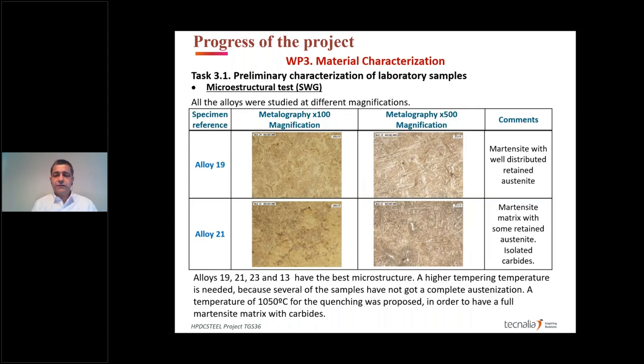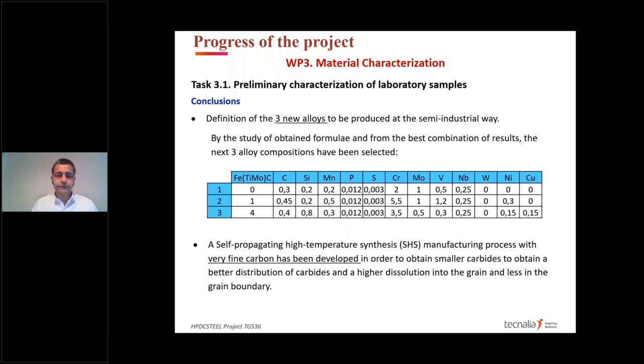From this, we also wanted to know what happened with the microstructure, if they were a good martensite structure or not. So in some of the cases, we have a very good martensite and well-distributed retained austenite. But we see also in some of them, and in many cases, it was not a good complete austenization of the steel. So we defined that we would increase from 1,030 degrees to 1,050 degrees for the quenching process, to try to austenize all the matrix.